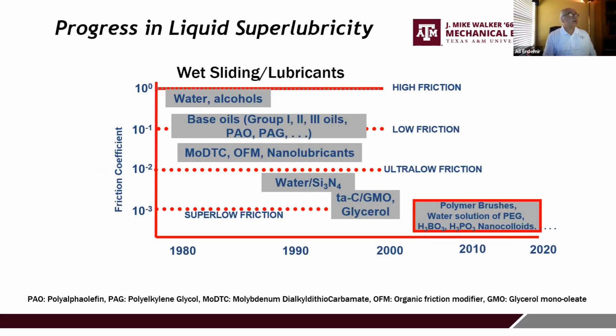superlubricity will be far more desirable. Not all liquids actually give low friction. If you apply water or alcohols to a sliding interface, you don't necessarily get low friction. But then you have all these base oils or synthetic lubricants like PAO or PAG. With the addition of these friction modifiers, the friction can actually come down. And there are special circumstances where water can actually be a marvelous lubricant for certain ceramics, by virtue of some tribochemical interactions, where surfaces actually become extremely slick.